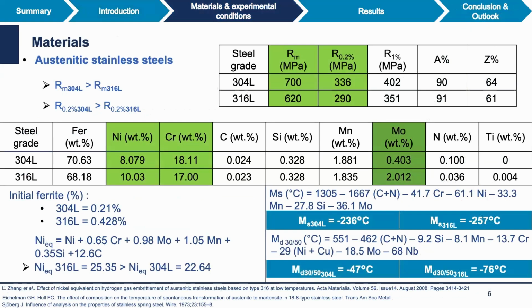So for this study, we selected 2 conventional grades, 304L and 316L. So this has been discussed during some previous presentations, depending on the chemical composition, and in particular the nickel equivalent index, you can have different stability of the material with respect to strain-induced martensitic transformation that you can characterize by the MS or MD30 temperature, for instance. And so, of course, in our case, we have a higher index value, even if it's not extremely high, in the case of the 316 with respect to the 304.